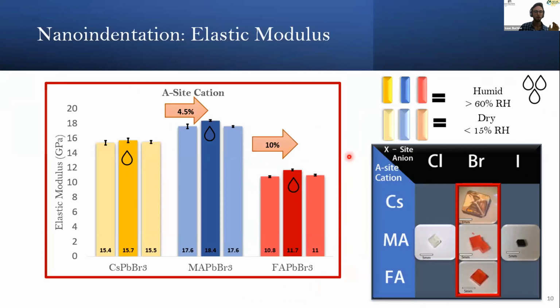And just to clarify how we perform these measurements, we take a crystal, we place it in the instrument of choice. We bring the crystal to a dry environment. We let it acclimate. We measure the crystal. We then increase to the humid environment. We let the crystal acclimate for 30 minutes. We measure on the same crystal in the same region. And then we repeat the process, but we go back to the dry setting. And on the same crystal and the same area, we measure the mechanical properties.